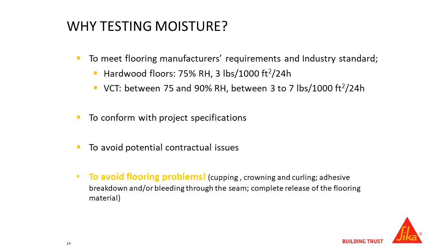Why do we test for moisture? Well, number one, we know that finished floor covering manufacturers have requirements, and then there's also industry standards required for installing finished goods. You see there, hardwood floors require 3 pounds on the calcium chloride and 75% relative humidity. VCT, you have a range there depending on the product, 75 to 90% relative humidity, 3 to 7 pounds on the calcium chloride. So that's one of the reasons why. We know the flooring manufacturers require it.